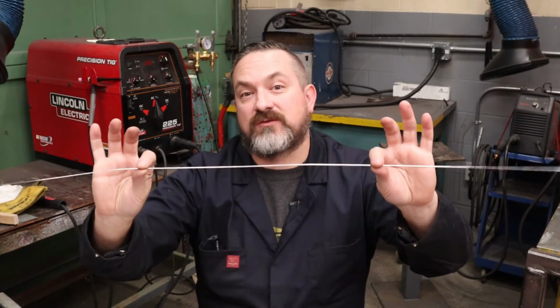Now, when you're picking your filler rod for aluminum TIG welding, you have two main choices that are going to cover about 80% of the different aluminums you're going to weld. Now, you have 4043 and you have 5356. Now, the 4043 is a very good general purpose rod. It has a slightly lower melting point, so it allows you to have a little less distortion in your parts and also reduce the risk of cracks. It should make very nice, clean, bright, shiny looking welds for you. And you'll notice that the weld puddle will be very fluid. It flows very, very nice when you're doing your projects.